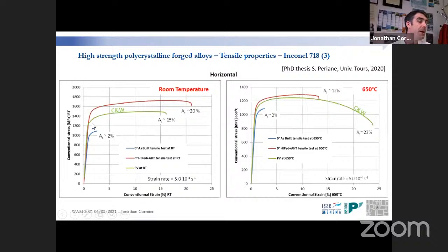So in each case, the green curve accounts for the cast and wrought material, conventional strain, conventional stress plots. And we can see that the as-built microstructure has a ductility of nearly 2% at each temperature. And something which is very interesting is to see that the HIPed material with optimized HIP cycles provides outstanding properties, very comparable to the cast and wrought material at high temperature, and surpassing the cast and wrought material at lower